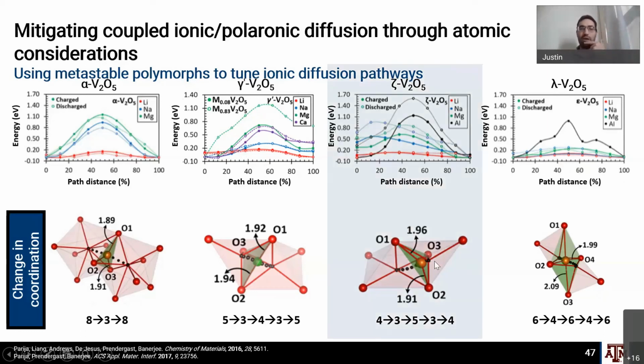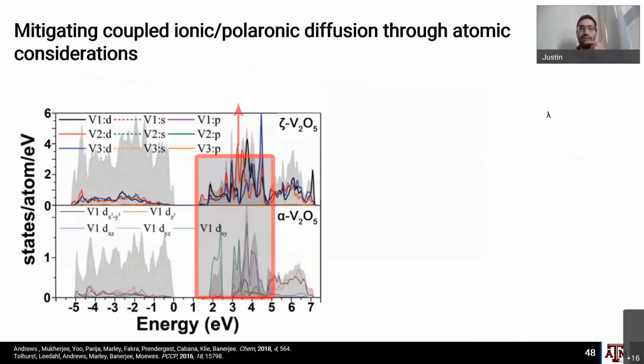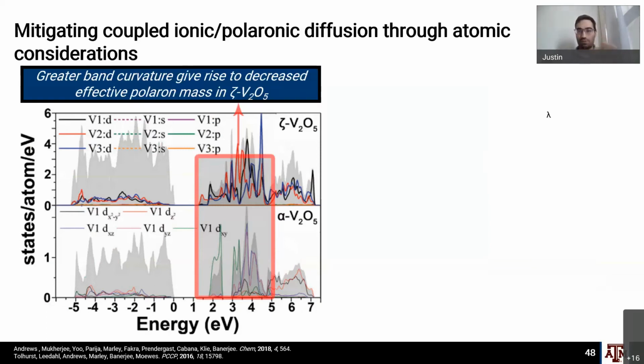So I'm going to be talking primarily about zeta V2O5. And by rearranging the V2O5 framework, zeta V2O5 has allowed us to not just intercalate lithium much better than alpha V2O5, but also achieve magnesium ion intercalation. I mentioned that a lot of the electrochemistry I'm going to be showing here was done in collaboration with Jordi Cabana's group. They did some really beautiful electrochemistry here in one of the first oxide materials that was shown to have magnesium intercalation.